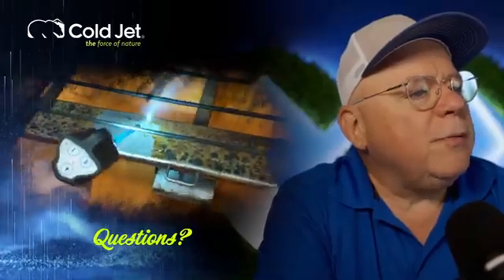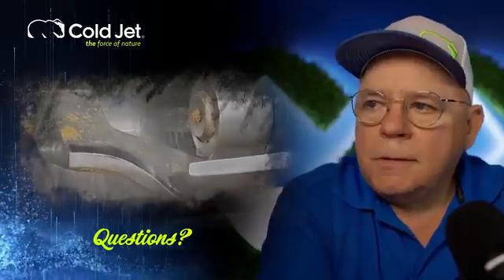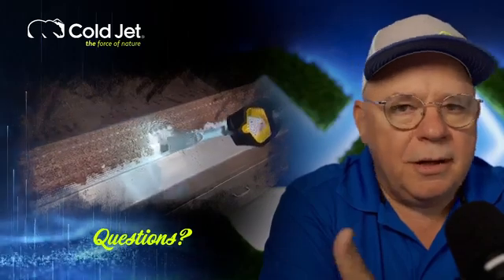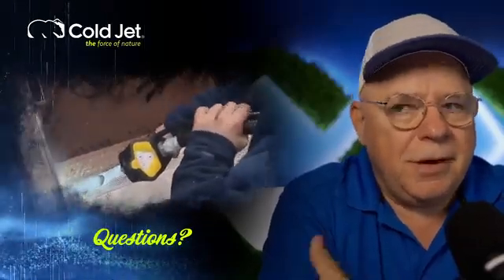I might have missed this part. How much does it reduce the time cleaning with dry ice compared to by hand? Well, the example I have is that oven they cleaned. It takes 3 days to clean that thing. By the time you shut it down, wire wheel it, soak it in caustic soda, put it back together, and heat it back up, days. I cleaned that thing in 2 hours. Every single thing is different, so it's hard to give an example. If you have something for us to look at, call us. We'll come out and take a look at it.